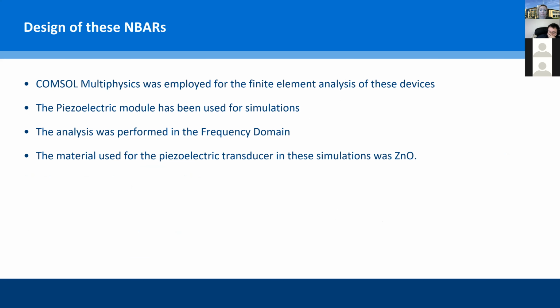For the design of these sensors, we have used COMSOL Multiphysics, and the piezoelectric module was employed. The analysis was done in the frequency domain, and the material we used was zinc oxide. Zinc oxide was used because if we want to go into real-time fabrication of this device, then zinc oxide is a really easy material to form based on the stoichiometric ratios, and also it's quite biocompatible. So if we want to go for a biosensor based on these nanoscale bulk acoustic resonators, we just thought it would be ideal to use zinc oxide for simulation as well.